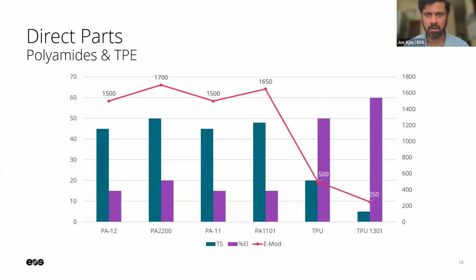So when we compare the properties with the VDA standard for additive manufacturing, our processes and the standards are matching. Unlike what we see in metal, where we have process-based standards, in polymers we have product-based standards. So we have to compare with products, but fortunately we have the VDA standard for additive manufacturing, and that shows clearly our properties such as PA2200 overlap with PA12, and PA11 properties which were set by the industry standard, PA11 matches, and so forth.